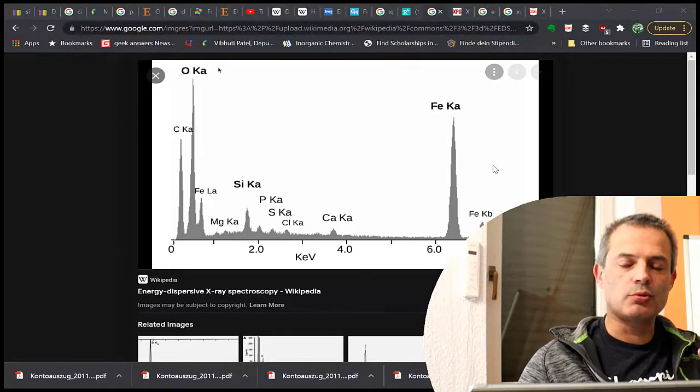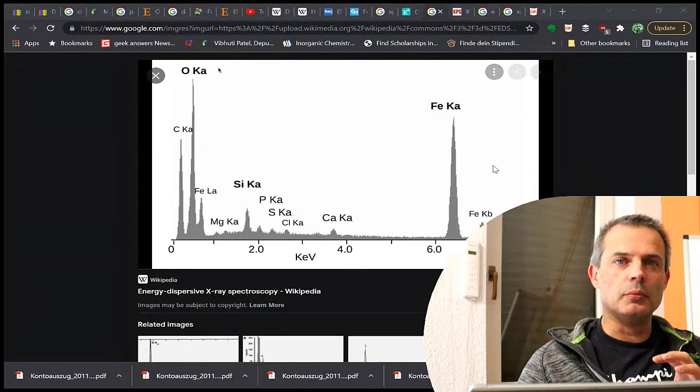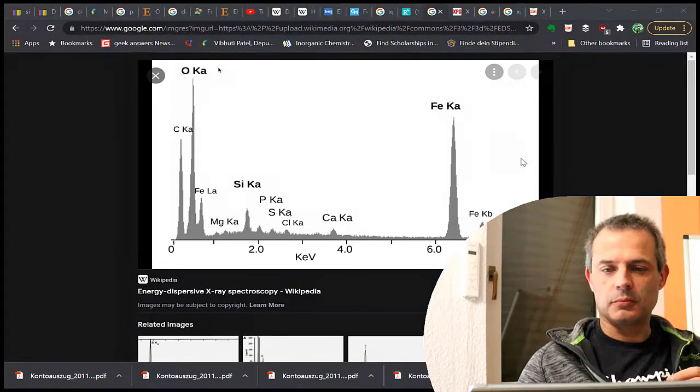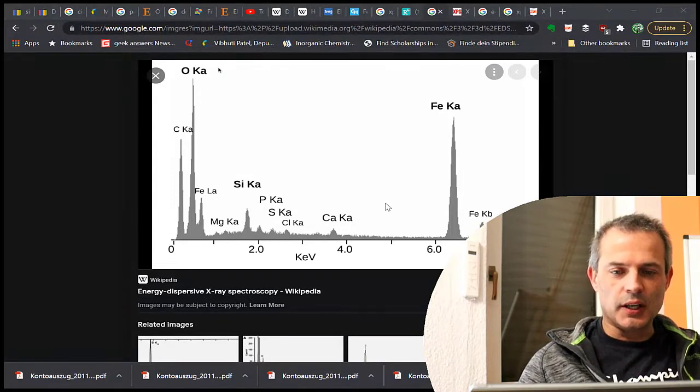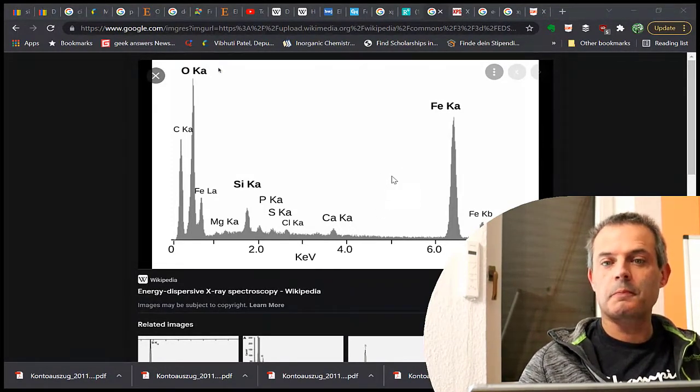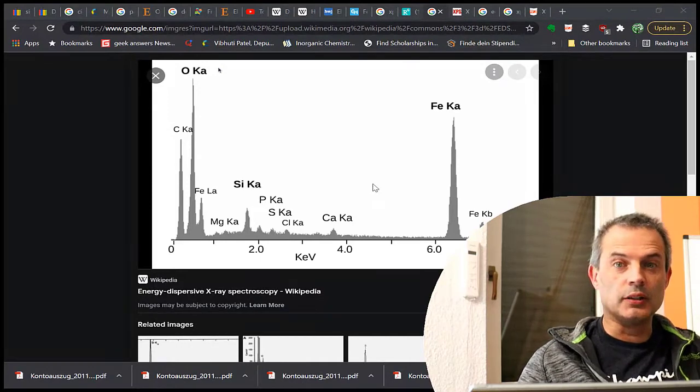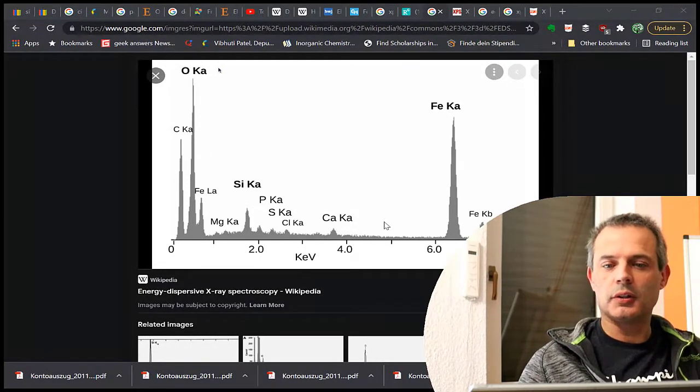Obviously we would typically try to take the peak with the most energy, with the most integral effectively, but we can see here, for example, the oxygen and the iron L overlap each other, and that is obviously a problem because we will have more and more difficulty extracting the real percentage of the oxygen in this particular constellation if we have more things underneath it.